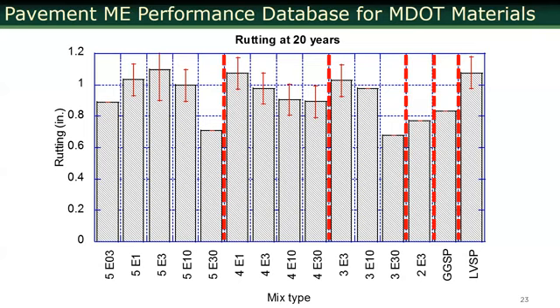Sometimes there is a binder grade change from the 3 to the 10s and the 30s. Exactly. Those are not considered at all. And also, this study is by no means complete, because here we did not calibrate the material models.